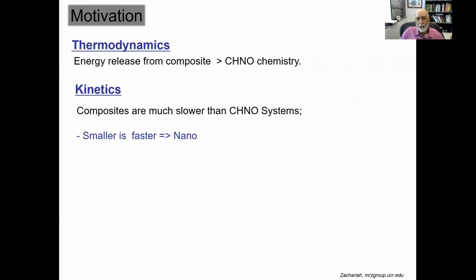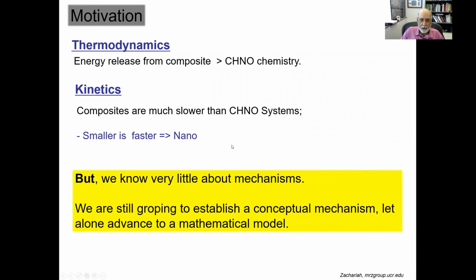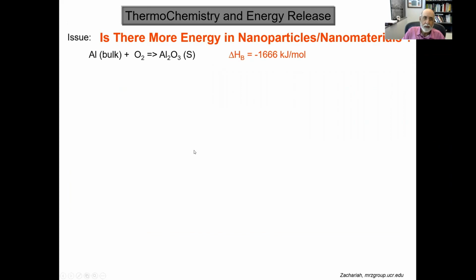So the motivation for understanding that, first of all, is going to be thermodynamics. We know the energy release is more than carbon, hydrogen, nitrogen systems, but the kinetics are going to be slower, which is why people have gone to nanomaterials, because diffusion lengths effectively are shorter. And so you go to a nanomaterial to do that. And despite that, they are going to be much, much slower than molecular systems. But we really don't understand these mechanisms. So if I just ask from an energetic standpoint, is there more energy in a nanoparticle?